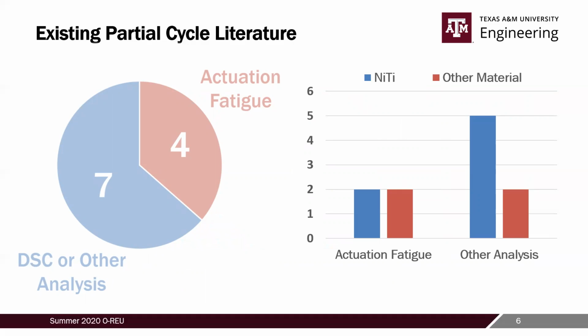But none of these partial cycling papers that I found studied nickel titanium hafnium, which was the material chosen for the NASA ULI project. So this shows how important it is that we study the actuation fatigue of this material, since there's hardly any literature in this area.